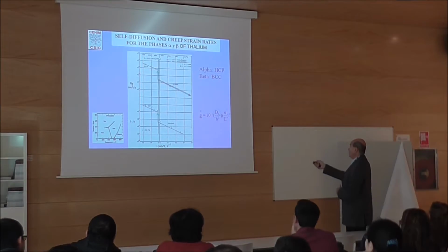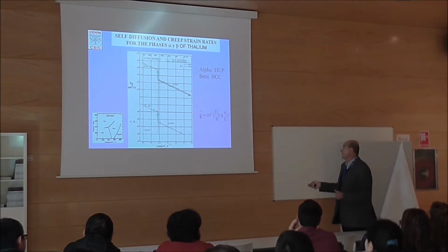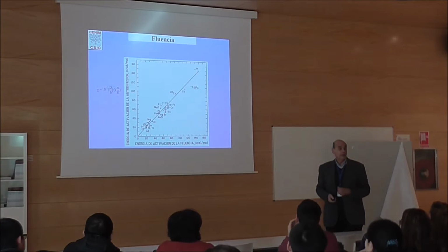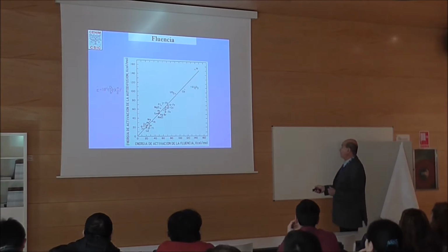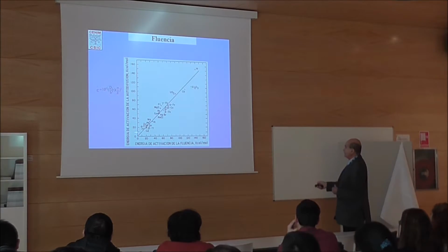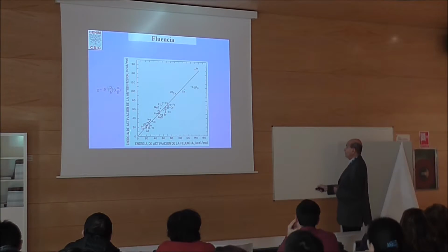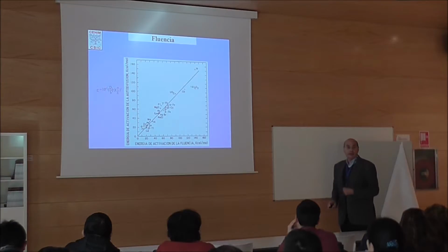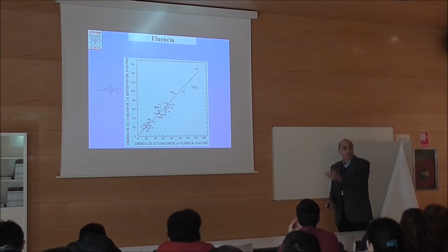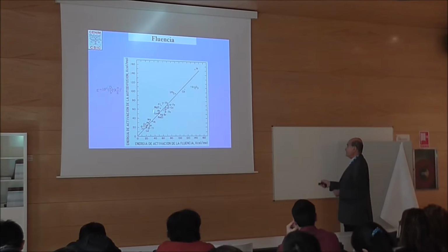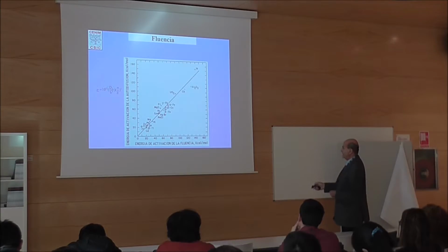So you have here only examples of 2 materials, but you can also go to the paper of Taleff. You have all these materials, and you see this is 45 degrees. This is the activation energy for creep, and this is the self-diffusion activation energy from the chemist. So you have a very good correlation. That's a test of the validity of this equation.